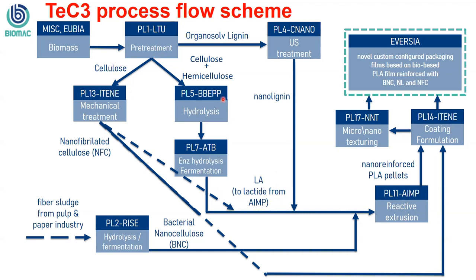And of course, in addition to the cellulosic and hemicellulosic components of the biomass, we also make use of the lignin-based material here. So there's an organosolv process followed by ultrasonic treatment to produce nanolignin, which is again, as I mentioned, one of our additives, giving us some stability, giving us some enhanced resistance to oxidation and degradation and things like this.